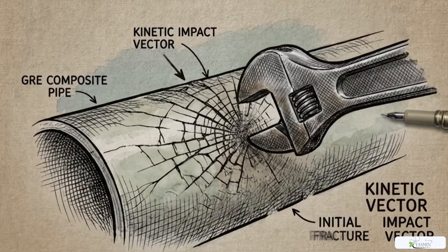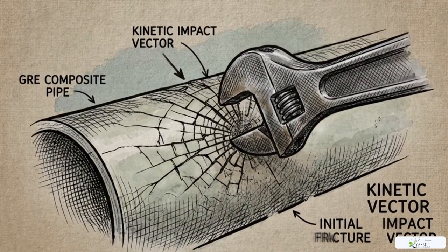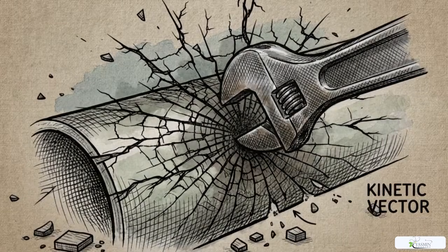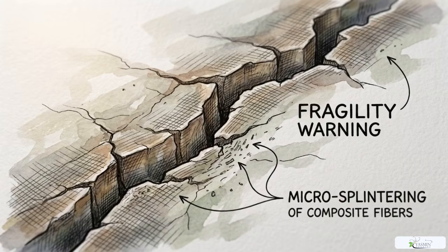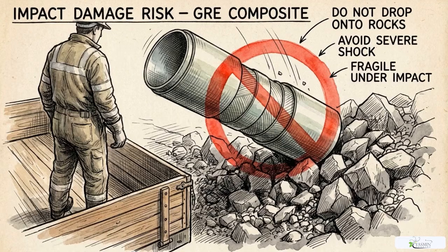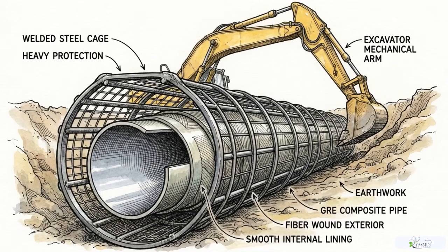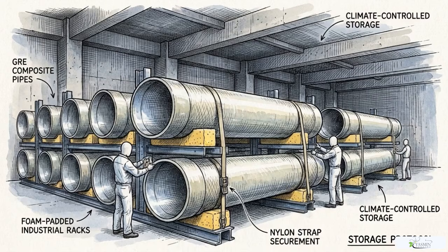The structural catch isn't the internal pressure, it is impact. The hardened resin matrix is incredibly brittle. A sudden external impact of anything over 25 joules is enough to crack or chip the pipe. In the field, this means GRE cannot be dropped off the back of a truck or dragged across rough gravel. It shouldn't be installed without heavy protection in zones where heavy machinery or dropped tools might strike it. The budget saved by not renting heavy lifting cranes generally needs to be reinvested into highly protected storage and strict handling protocols.